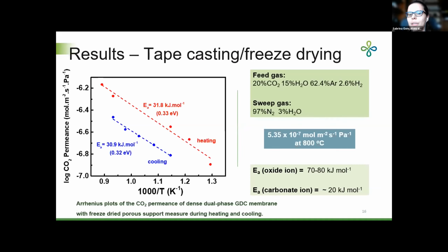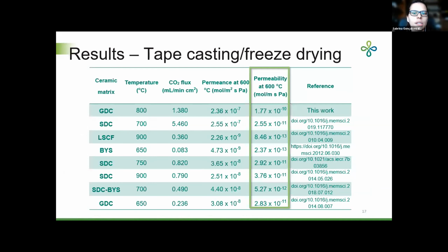This indicates that the permeation is in a regime of mixed kinetic control. This means that the permeation is not limited either by the carbonate phase or by the ceramic matrix. And this table shows the flux and the CO2 permeation data from different studies.